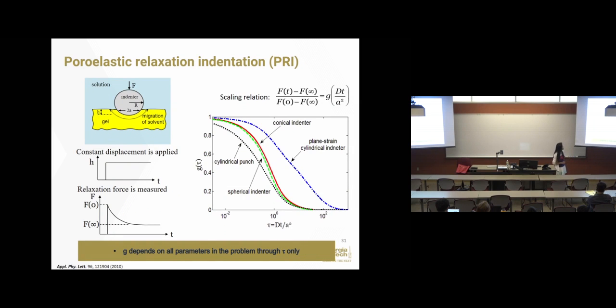So here is actually my PhD work many years ago when I was working with Zhigang. We look at this relaxation method, and we found that actually for this complex problem, we can find a very simple scaling relation that if we normalize the force relaxation curve in this way, it becomes a function of one single non-dimensional parameter, Dt over a squared. D is diffusivity, a is contact radius, right?